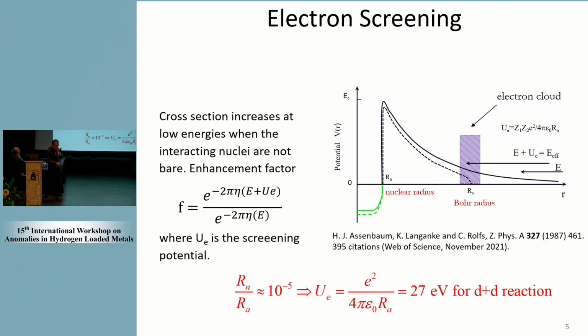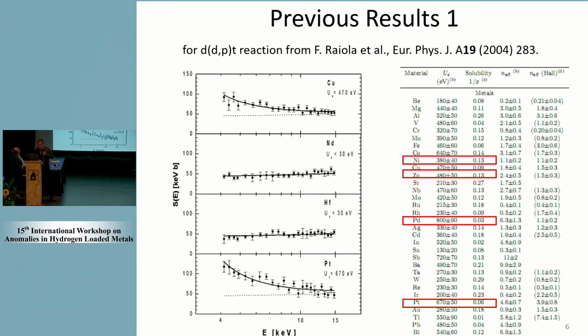Another point is that this picture also works inside the nucleus. The protons are actually bound more inside the nucleus than they would be without those electrons, so this also needs to be taken into account. Claus Rolfs and his group measured all metals, and in many cases they got electron screening potentials much higher than this prediction of 27 electron volts. The highest one, as Natalia said, was measured in palladium, 800 electron volts.